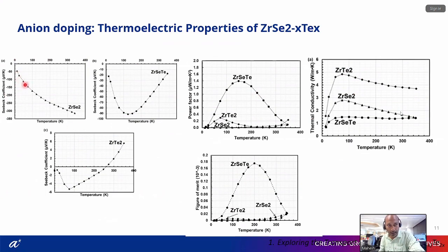where we got, sorry, I don't have the electrical conductivity. Seebeck coefficient is like p-type, then it decreases with the selenium. It is like a semi-metallic compound. When it is more semi-metallic, it's like crossover behavior. This is also observed in cation doping with vanadium and molybdenum doping at the zirconium site. Like the band, it depends on the lattice constant variation. So a small strain can change from p-type to n-type. So I'm going to decide the composition less than 1, with less tellurium content, on the selenium-rich side, to tune the electrical and thermoelectric properties rather than the higher tellurium content.